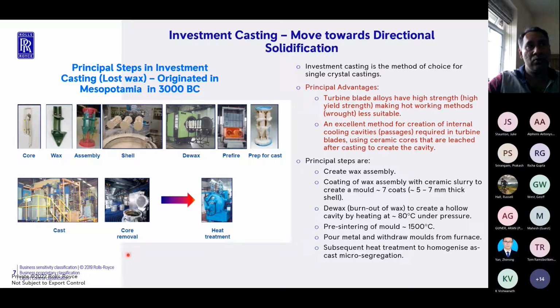So what do you do? You use either sodium hydroxide or potassium hydroxide under pressure, in the boiling form. And effectively, the potassium hydroxide or the sodium hydroxide leaches out the ceramic. And what you're then left with is a blade which has got the solid metal with a hole or a cavity, which has now been created because this core has been leached out.